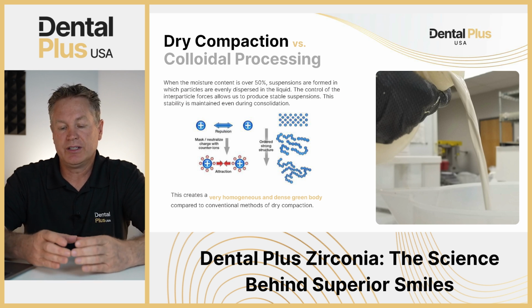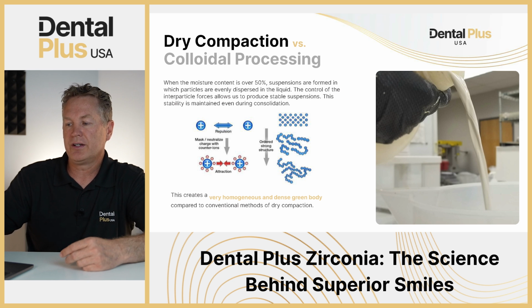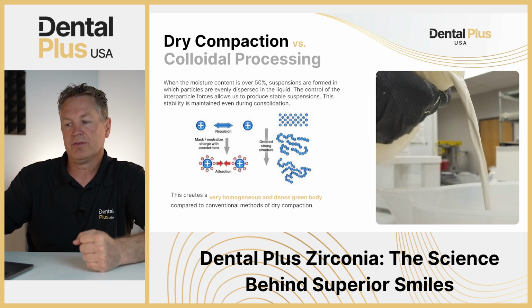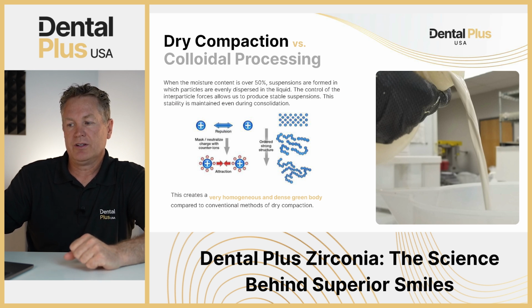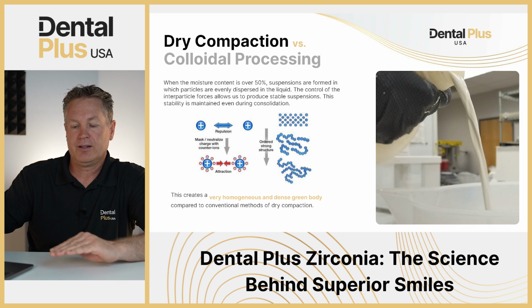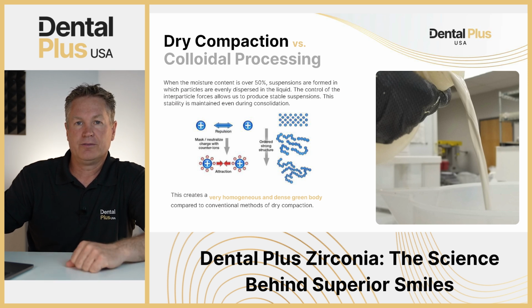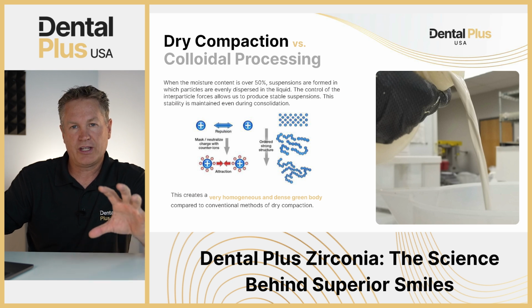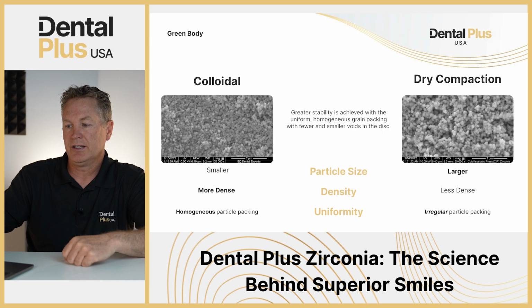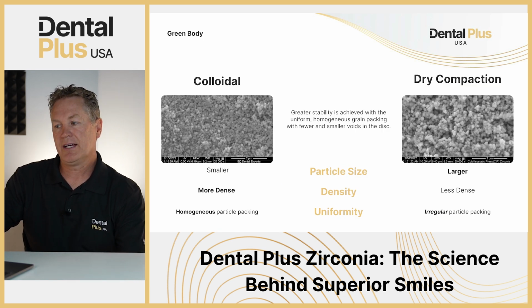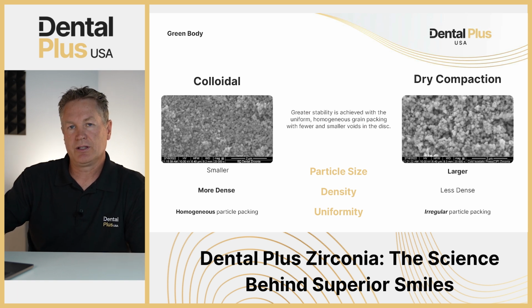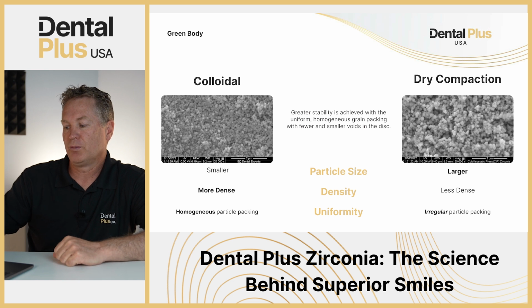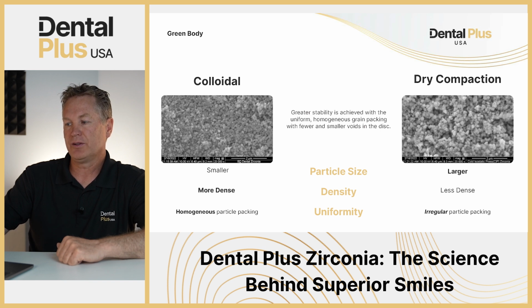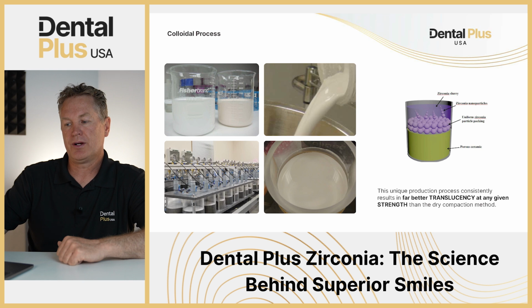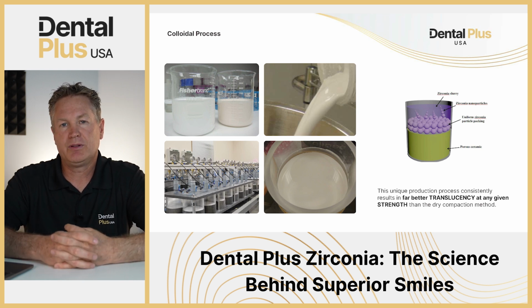Once you pour these into the molds, it creates a very homogeneous and dense green body compared to conventional methods of dry compaction. So you get very homogeneous, dense particles all laid out. You don't have voids in between them, and you don't have big particle sizes and small particle sizes. You'll see a difference where you have the particle size on the right hand side showing the dry compaction, and one on the left side showing the colloidal. With this, you can see the difference between the homogeneous laying of all the particles compared to the other one. It's basically irregular particle packing with dry compaction compared to a more homogeneous particle packing with the colloidal side.